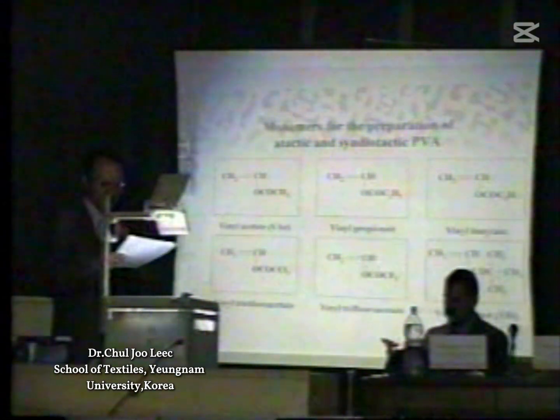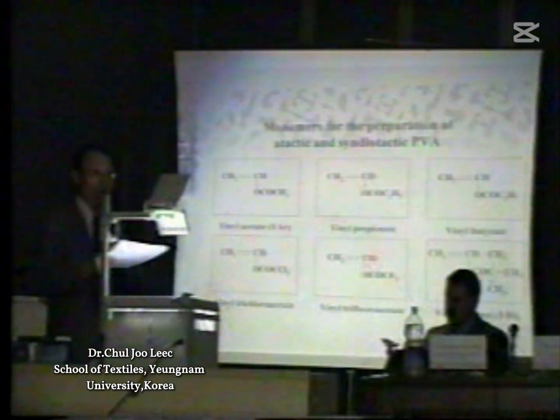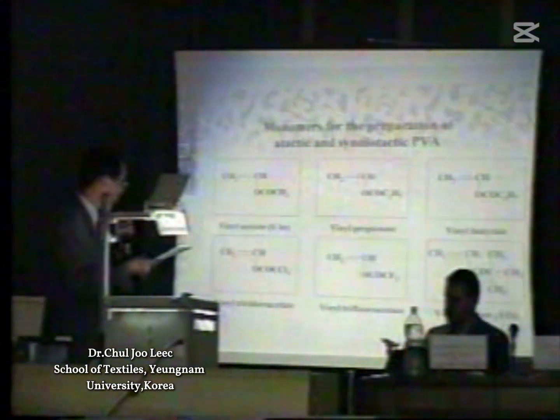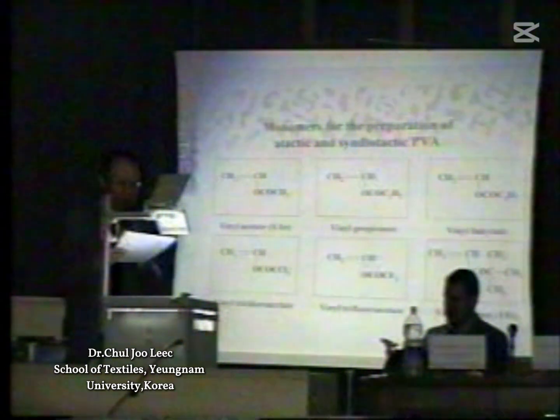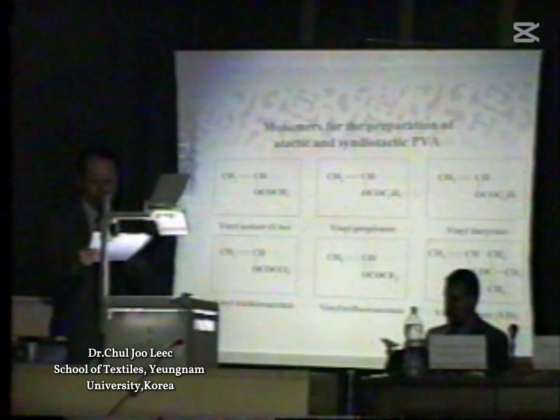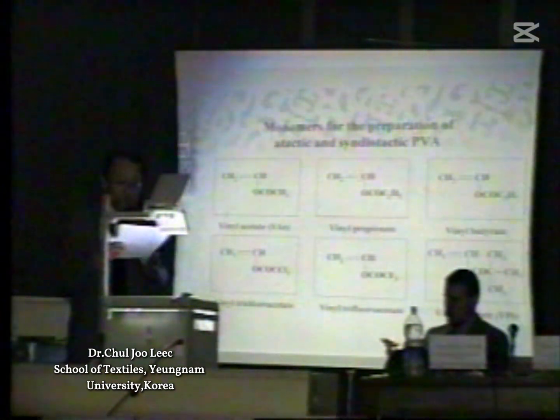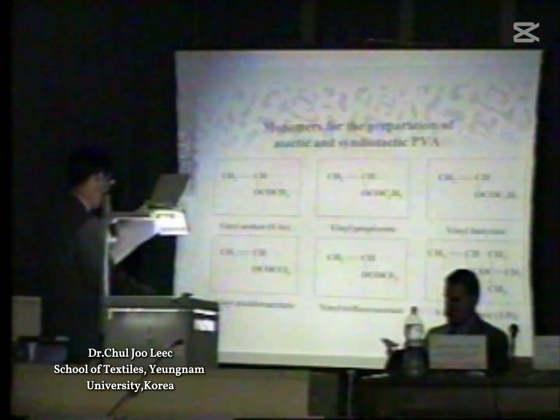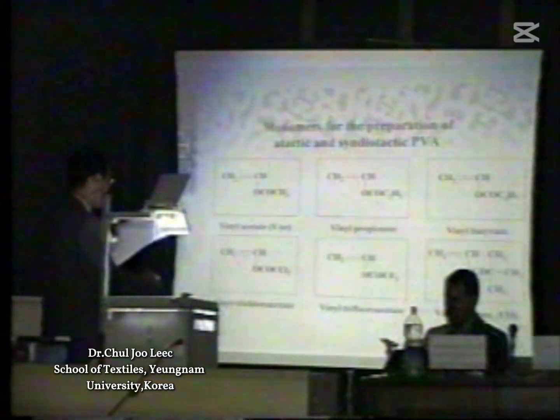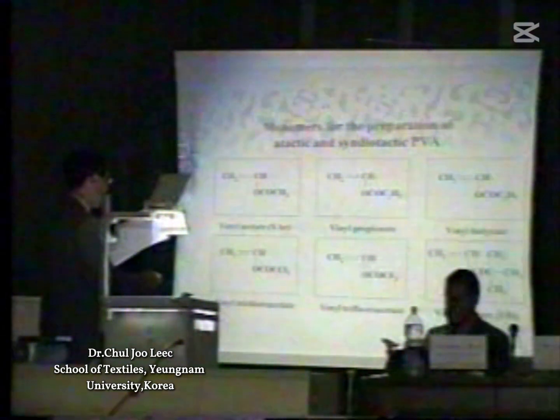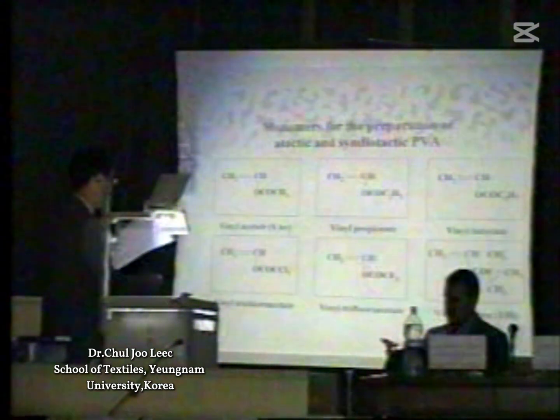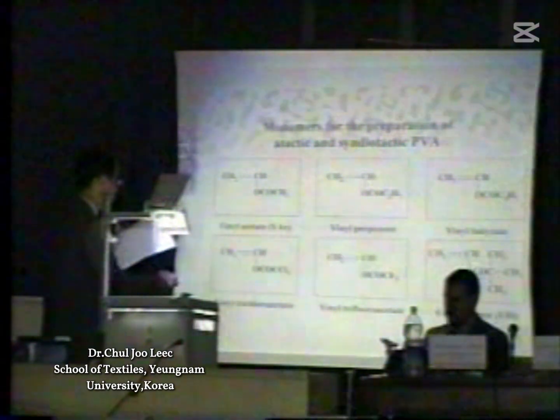These are the vinyl ester monomers for the preparation of PVA. In order to make highly syndiotactic polyvinyl alcohol, we should choose a vinyl ester with bulky pendant groups, such as vinyl trifluoroacetate or vinyl pivalate. These two kinds of monomers have very bulky pendant groups.